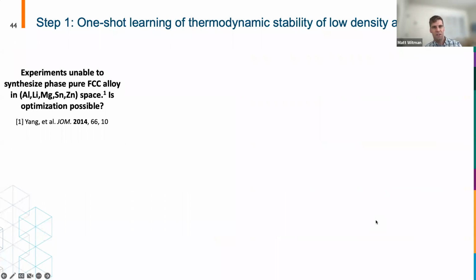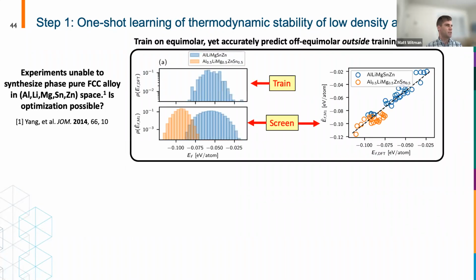So I see that I have only about 10 minutes left, so I'm going to quickly jump through this and just say that basically, if you give these models a specific training distribution, they can actually do out-of-distribution predictions quite accurately. When I screen a different composition than it was trained on, or different equimolar ratios than what it was trained on, we can actually accurately predict those configurations.